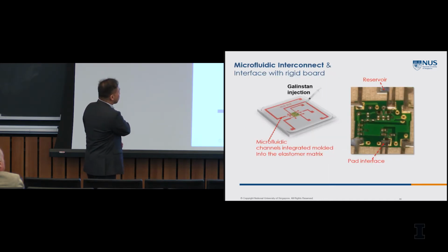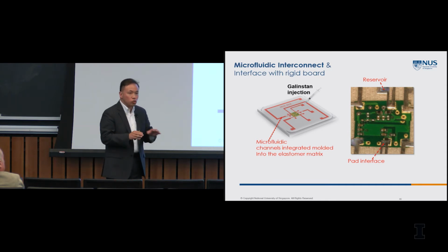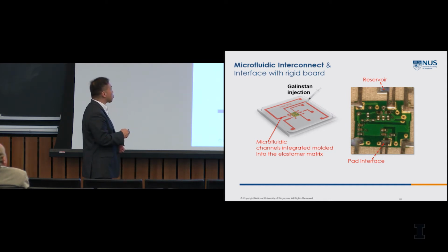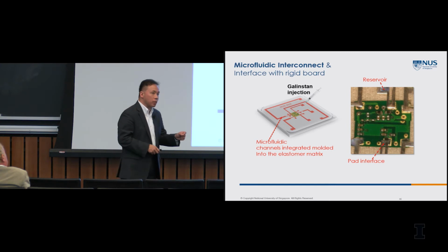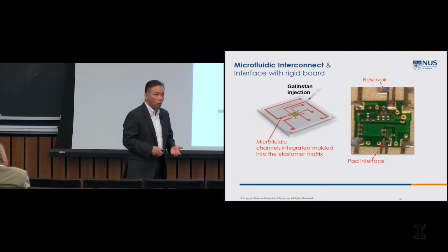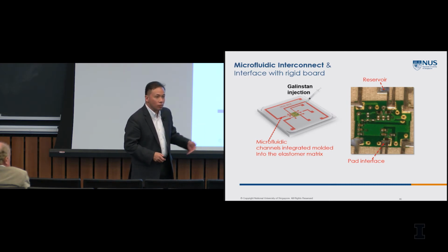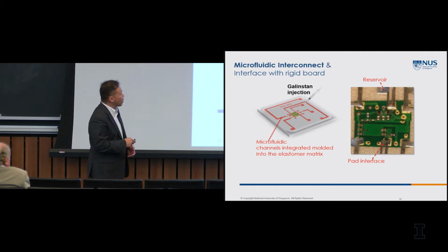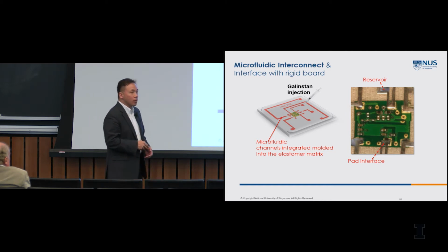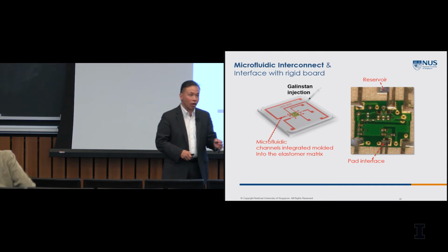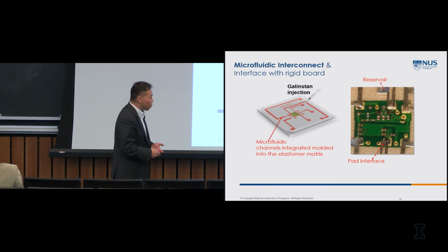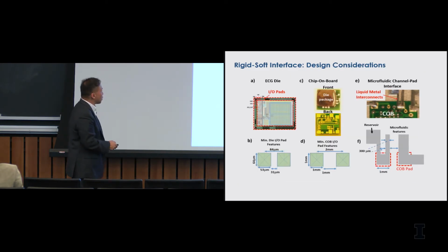And the interesting part about integration is we molded the entire chip into PDMS, which is silicone, right? So effectively it's encapsulated. And then we create these channels where we inject the gallium liquid metal to interface with the pads. So the pad design is very important because these channels can't be too small. They're limited because you're actually getting fluid through the system. So it has to be designed in a way that there's a bend. Just imagine if it terminates at the pad, effectively you have an air bubble that gets trapped there. You never have a connection, right? So that's another interesting part of the integration. The key is designing the pad such that it interfaces well with a reliable pattern of the microfluidic structure.